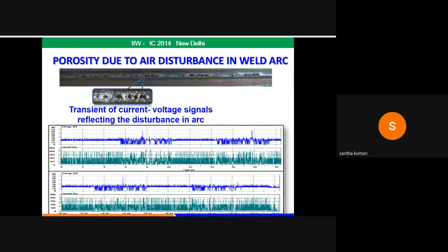The air is paused for a duration of 5 seconds and then closed, and you can see here another 4 seconds to allow the welding arc to stabilize again. We used a robotic station for doing these welds, because to have consistent welds we use these robotic stations. The process is repeated cyclically 4 times so as to create a disturbed signal and a stable phase in the arc, and a similar discontinuity is created in the weld.